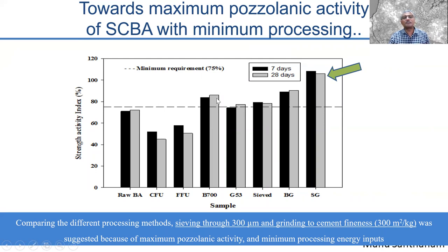But burning involves a lot of energy expenditure. Can we cut that down somehow? So then what we did was we found that sieving the material through a 300 micron sieve was sufficient to actually get the activity index to the minimum requirement. Sieving and then grinding extended that performance even more.